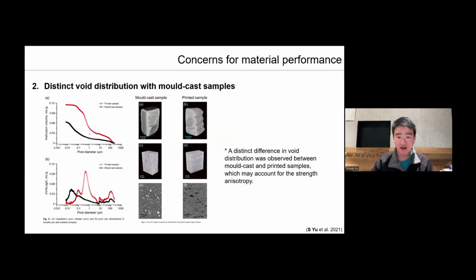To have a better understanding of the anisotropic behavior, we conduct void analysis using CT scanning and MIP test, then combine the results into a single graph. From the graph on the left, you can see the printed sample tends to have more small pores. The main reason is that 3D printed concrete doesn't go through the usual compacting and vibrating process, which in traditional casting helps eliminate the micropores.